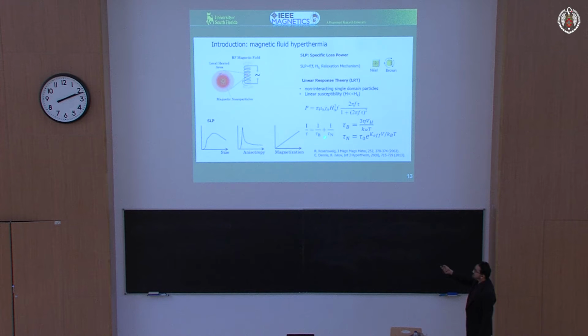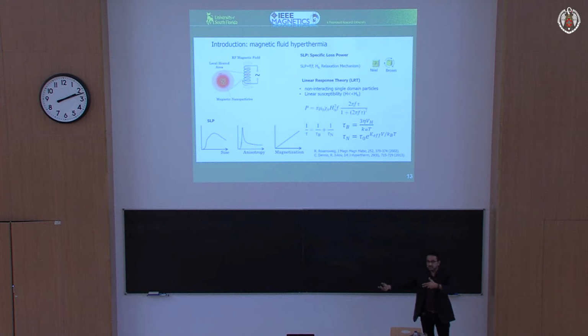There are two important time scales here. One is called tau B, which is the Brownian relaxation time, and the other one is tau N, which is the Néel relaxation time. Remember that if the environment allows it, particles can rotate. They can physically move, and this can result in Brownian-like motion, and you have a relaxation time associated with that. And of course, the Néel relaxation is with the coherent rotation of the magnetic moments of these single domain particles or small particles. Okay? So it's a combination that gives rise to the effective time, which goes into this equation here.